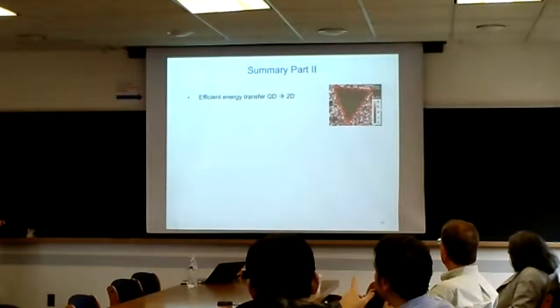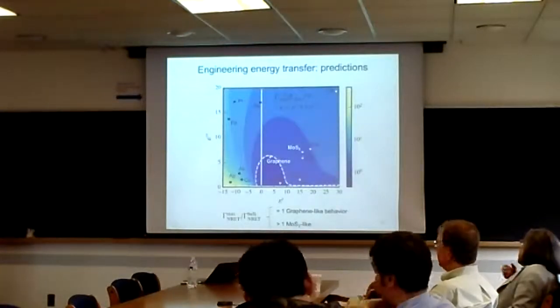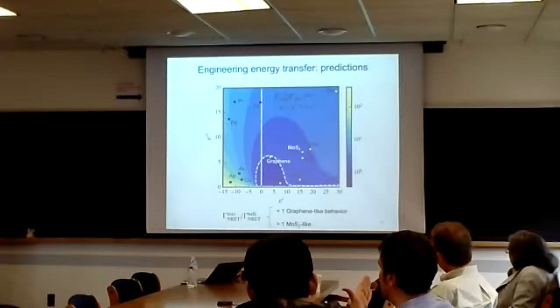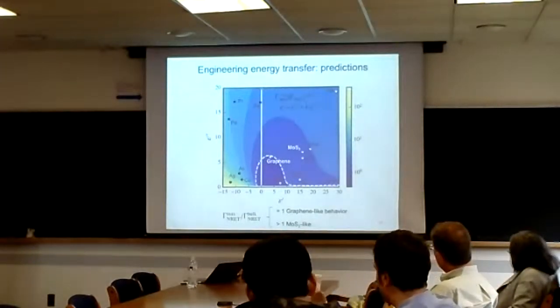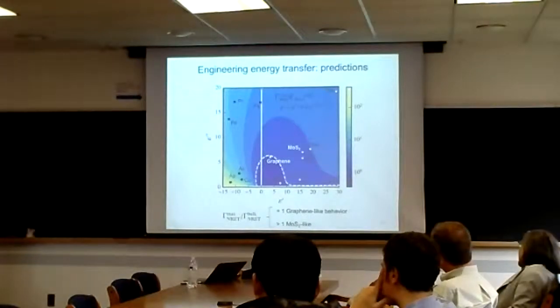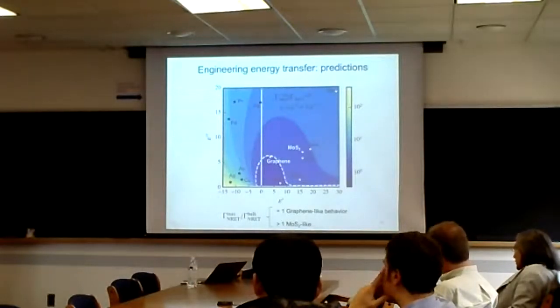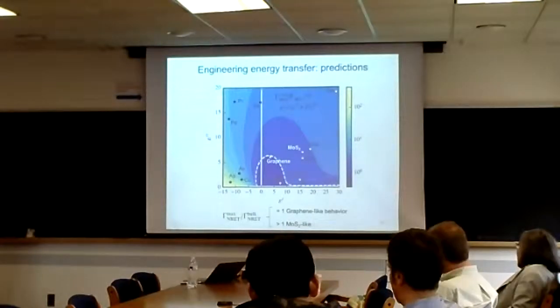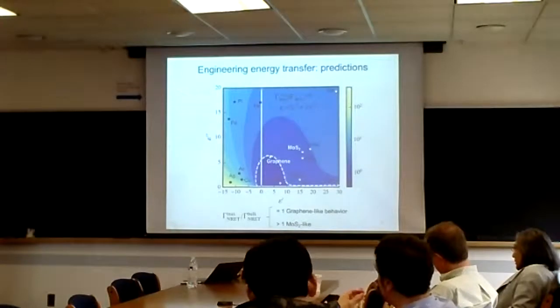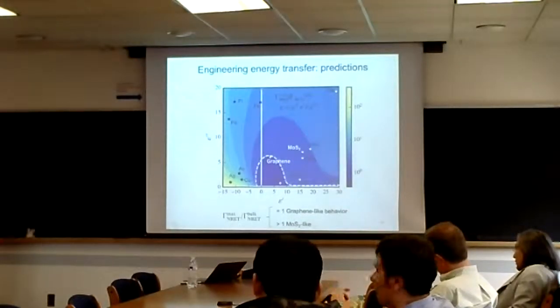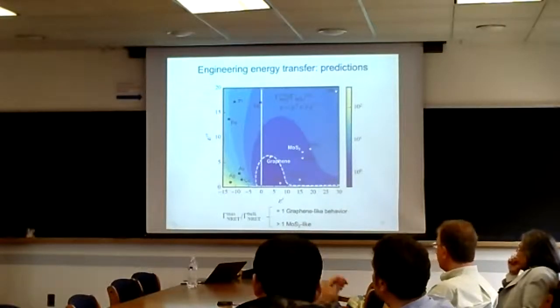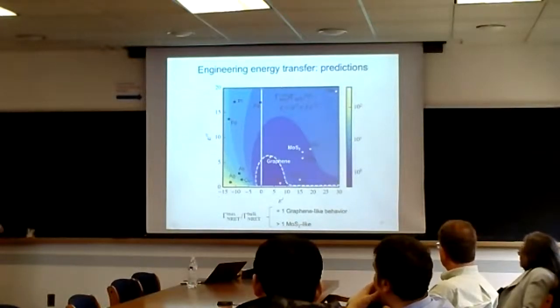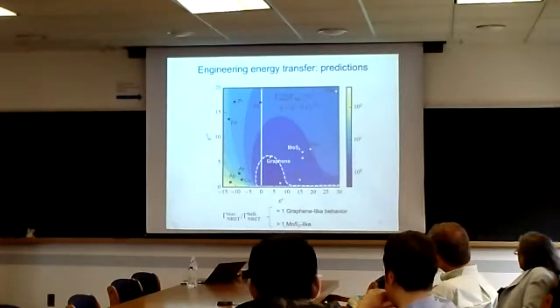So to summarize, can you go back one? Sorry. No worries. So for me to take home, is there anything special about the 2Ds? In this whole color plot, if the 2D didn't exist, couldn't I do the same with a bunch of ferroelectric metals? No, the reason the 2D had to exist here is because you had to make something that was half a nanometer to observe this thickness dependence. But let's say I was able to make strontium titanate in monolayers, which somebody can do. Would that do the same thing? It depends on the gap, but yes. Whatever dielectric I can grow in monolayer form. If you can do it, it doesn't make the TMDC or graphene anything special. It's just that it was an easy system to show this. Understood. Okay. Very good.